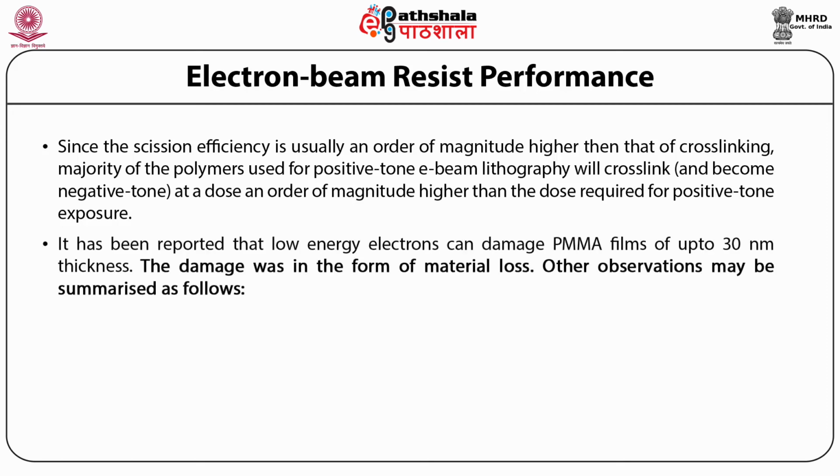It has been reported that low energy electrons can damage PMMA films of up to 30 nanometer thickness. The damage was in the form of material loss. Other observations may be summarized as follows.